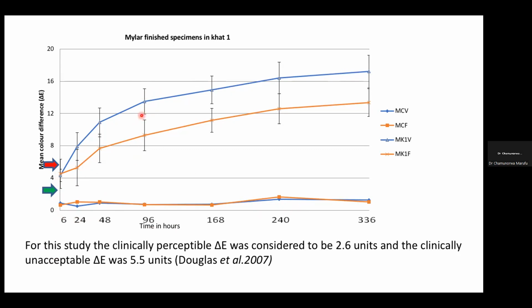And each group had 5 specimens, and the error bar still shows the variance in these specimens. And then this will just be comparing the two materials. The graph will be the microhybrid, which is Vit-l-escence, and then the orange line would indicate the color change in the Filtek, which is the nanocomposite. And then the 2 lines at the bottom, these are the control groups. Same materials as in the blue is still for the Vit-l-escence, and then the orange is for the Filtek, but these were in the control group, which I've already said was water.